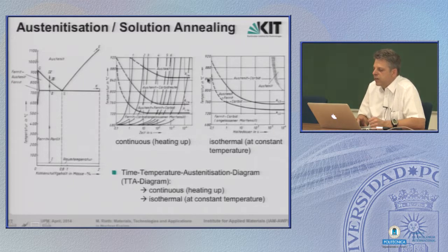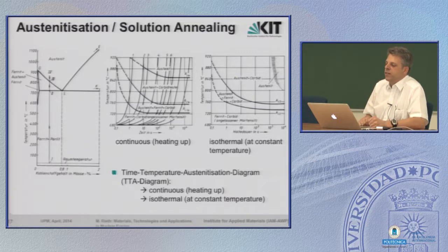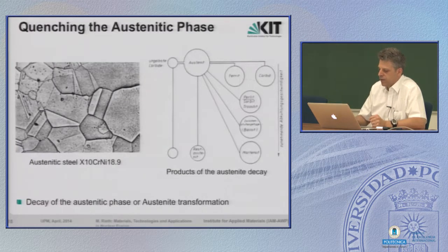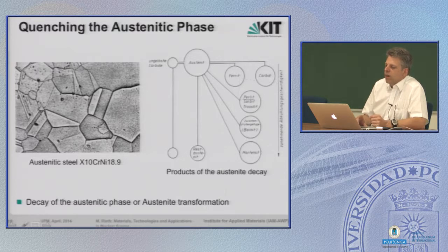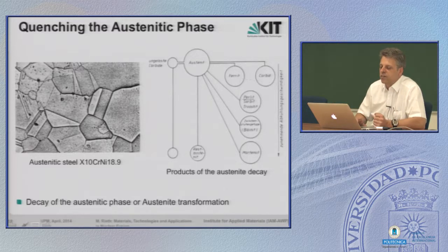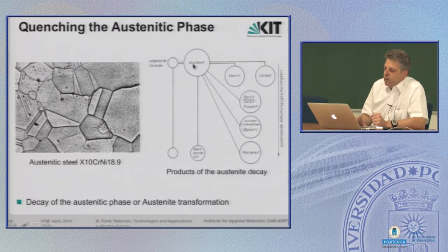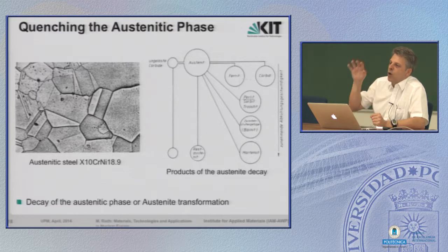Depending on time, here in seconds, it needs 10,000 seconds at that temperature to reach this austenitic phase. From now on, we consider that we have, as a starting point here, fully austenitic phase. Everything else has been dissolved. Then the microstructure should look like that. That's a typical microstructure of an austenitic steel, but in an iron carbide austenite phase, it will probably look the same, I will show you later. This is our starting point, 100% austenite, and now we cool down.